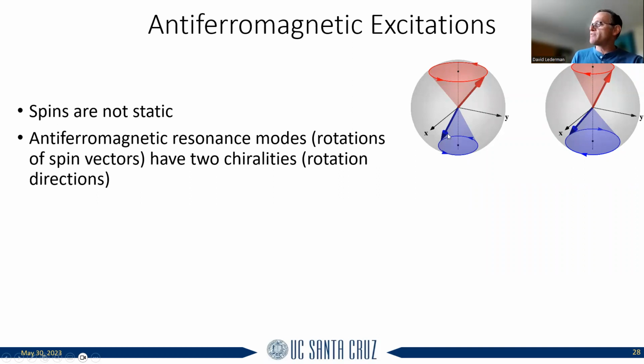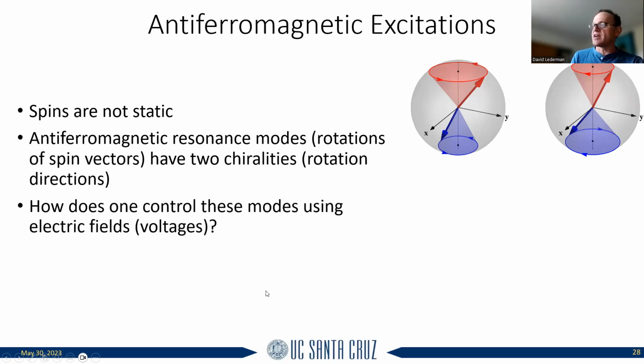Okay, so you can have, for an Ising antiferromagnet, well, it's not exactly Ising, but an antiferromagnet with a strong uniaxial anisotropy, like iron fluoride or manganese fluoride, two degenerate modes. That means they have the same energy, and they look like this. One of them precesses in this direction, counterclockwise, and this one precesses in the opposite direction. So they have opposite chiralities.